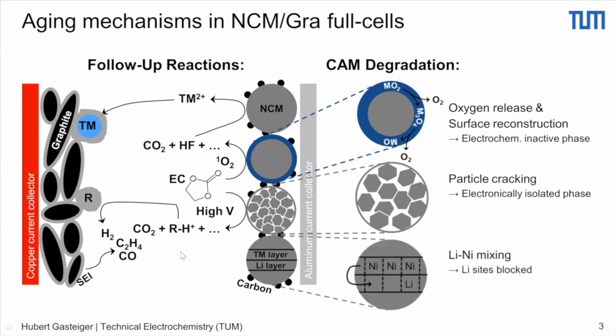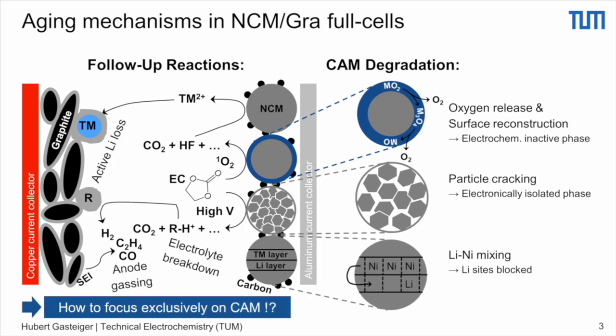And then of course we have a third mechanism, which is the so-called lithium nickel mixing, particularly well known for LNO. And the hypothesis there is of course that these lithium sites occupied by the transition metal lead to slower diffusion. So the question is, how do we do a study where we exclusively focus on the cathode active materials?